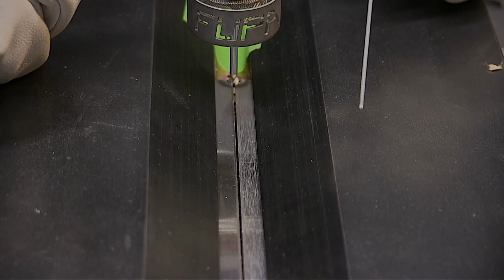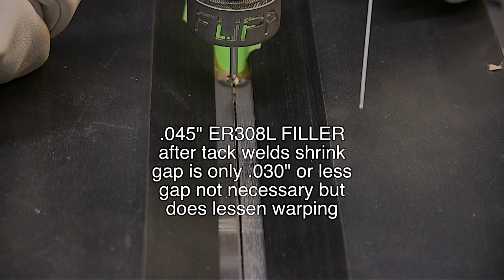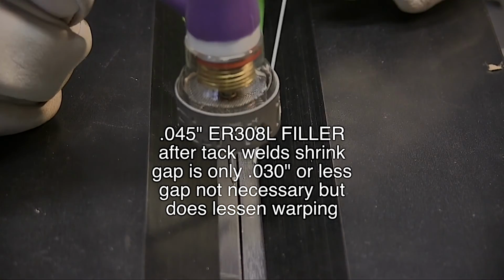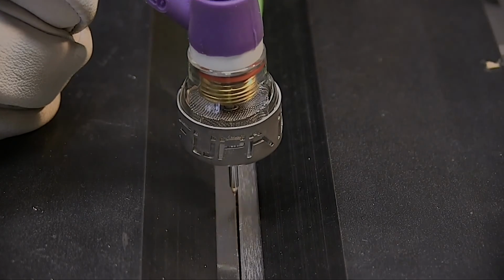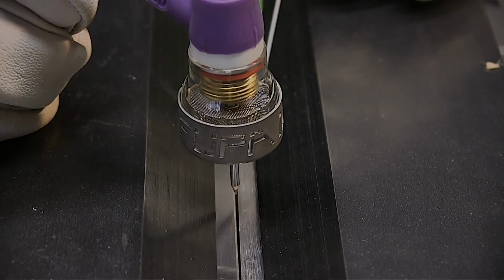The reason I gapped it, two reasons. Number one, it helps it distort less. And even though I gapped it about, say, .040 or so, it pulled shut to where it's less than .030 now, and it just really helps me see the line. It's not at all necessary to have a gap to get full penetration on something this thin. But sometimes it just depends on the alloy. Sometimes a gap helps. Sometimes it hurts.